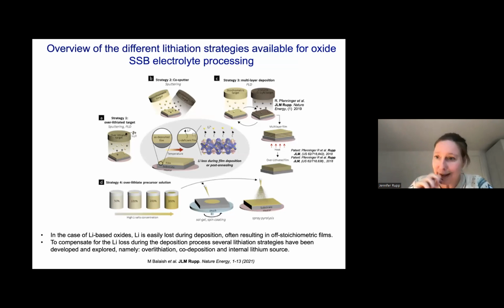And here's why. We live from structures that are beautiful conductors because they have enough lithium in them to phase stabilize a structure that is normally not very stable. And that's why the lithium can actually diffuse very well, hopping through defects in these materials. And the way to do that, in traditional powder processing, is that you over-lithiate a powder. So you offer much more lithium than it needs, so that when you go into high temperature processing and sintering, there's still enough lithium there to keep the phase in check that is the highly conductive one. That's what you do with lithium garnets or perovskites or many other materials.